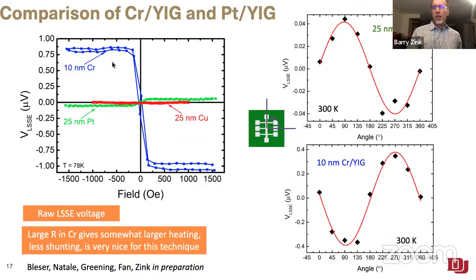Also, I'll just say, the fact that our chromium here has a quite large resistance is really great for this local spin-Seebeck technique, because the high resistance creates a larger thermal gradient from a given current that you push through it. And so that's part of what's going on, but again, significant spin charge conversion is also happening in the chromium at this thickness.